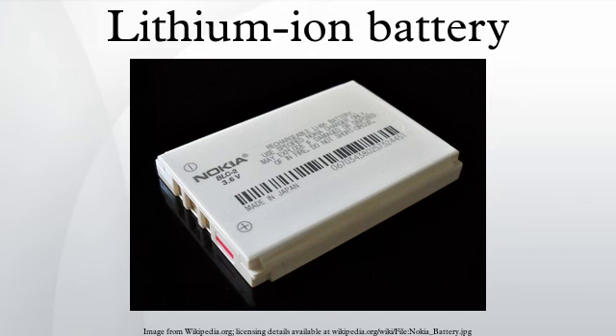For example, ethylene carbonate is decomposed at a relatively high voltage, 0.7 V versus lithium, and forms a dense and stable interface. Composite electrolytes based on PEO, developed by Syzdek et al., provide a relatively stable interface. It can be either solid and be applied in dry Li polymer cells, or liquid and be applied in regular Li-ion cells.